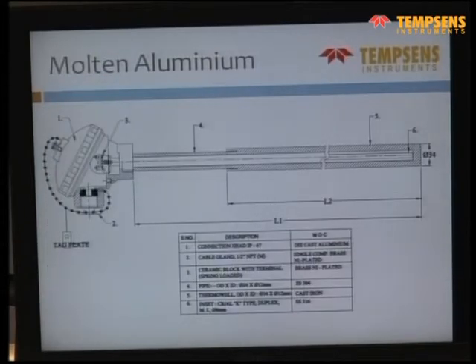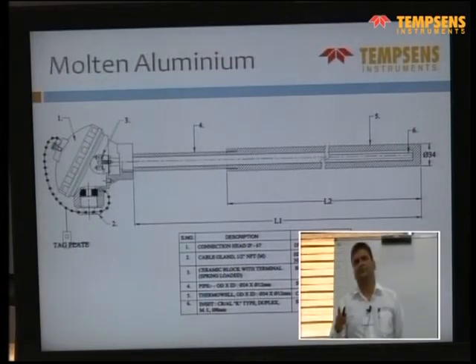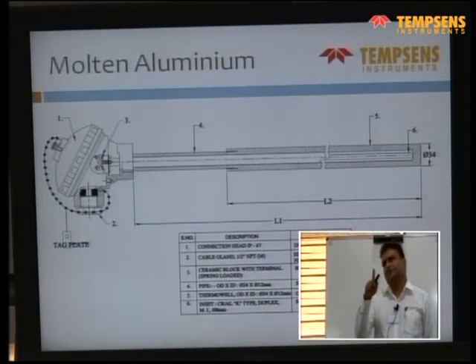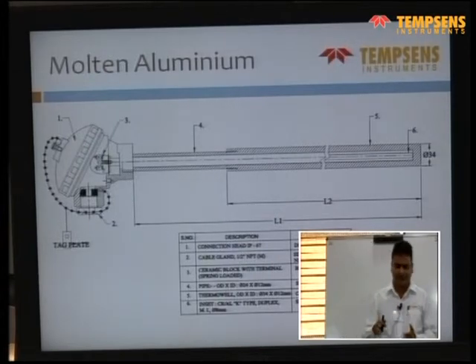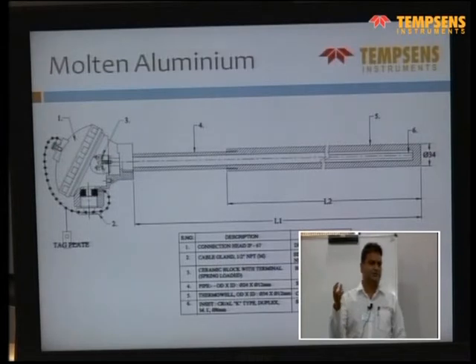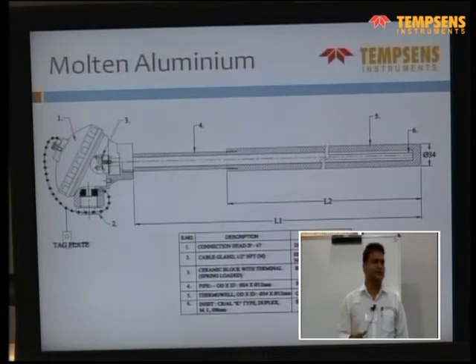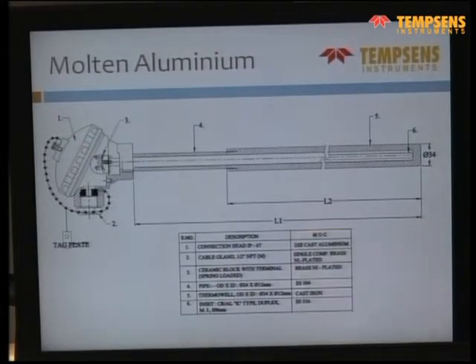There are other solutions with 446, or with cast iron. Cast iron is dissolved a little bit, and that kind of impurities go into the molten aluminum, but this is a much cheaper solution than a silicon nitride solution. But still it can give 1 month life to the customer. Some molten aluminum users use this, especially when they are charging with scrap. In case of scrap, the ceramic tube in the last case can break, but here the scrap is not going to, even with mechanical shock, this can give a reasonable life.